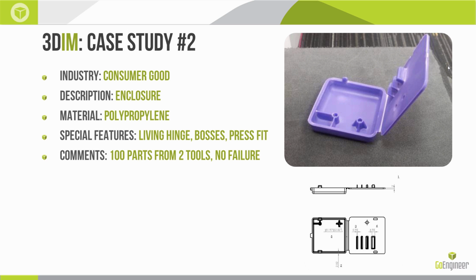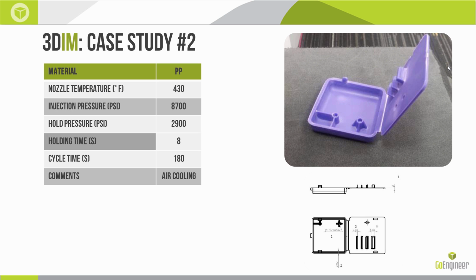The reason for that is the polypropylene has a good flowability and a relatively low melt temperature. So the nozzle temp was a little bit higher on this, 430. Injection pressure and hold pressure relatively the same, a little bit less hold pressure. Cycle time about cut in half, and we had air cooling on this. So that means after the mold was separated, the part itself was hit with an air nozzle, and that helped cut the cooling time and the cycle time.